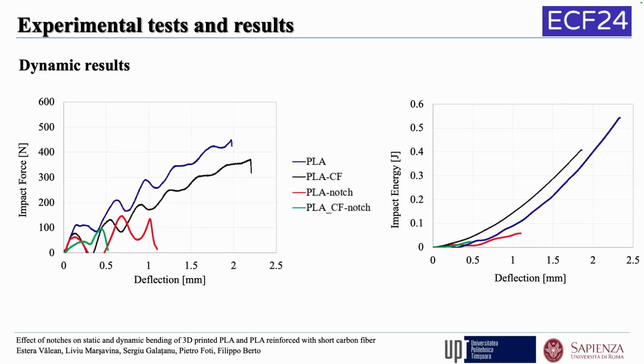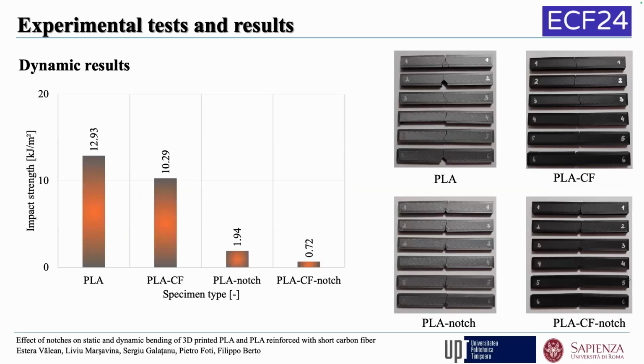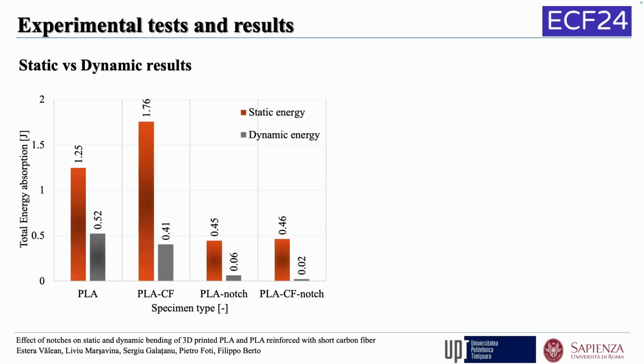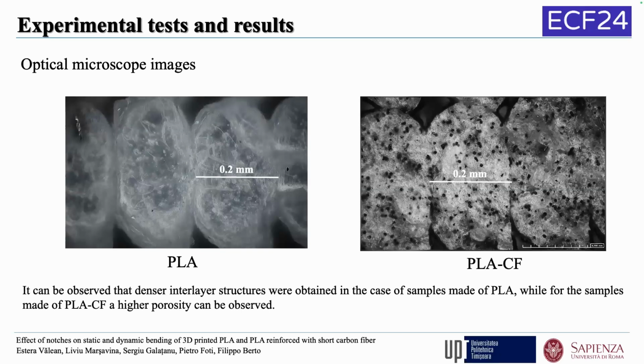So some results from the impact test. We have here the impact force versus deflection and the impact energy. In this case, impact strength also for the reinforced PLA is lower than for those tested on only PLA specimens. The total energy absorption comparison between static and dynamic results. So I mentioned that in static results we have higher energy absorption for the reinforced PLA. In the case of the dynamic load, these are not the same, so they are lower values. So we want to see a little bit why the results are like this, because we expect to have better results for the reinforced specimen, at least for the modulus of elasticity.